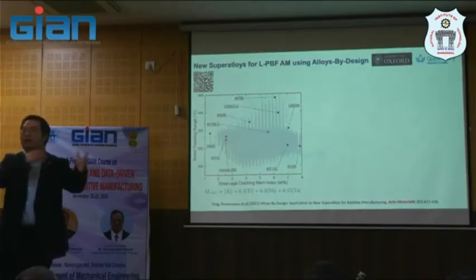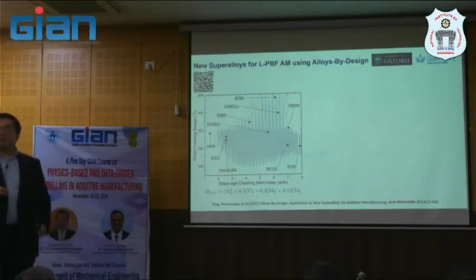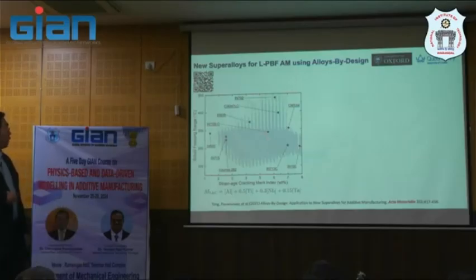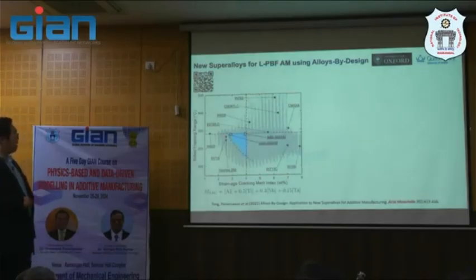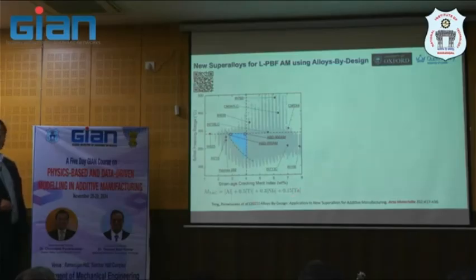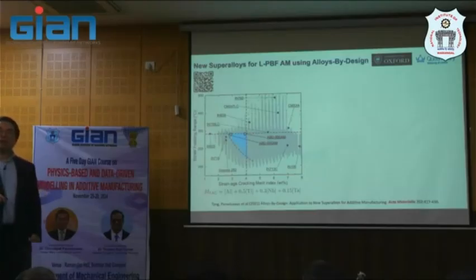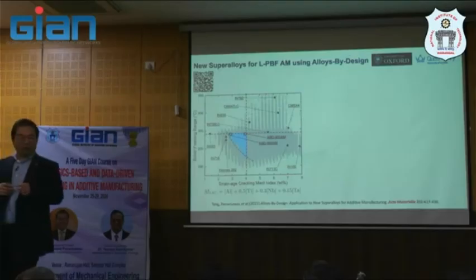We screen, rank, and do a lot of calculation based on the existing nickel-based superalloy database. What we did is use two indices here. I think I repeat it again. One is the strain-age cracking Merit index. Again, this is linked to the gamma prime fraction, but we add niobium and tantalum, which are small fractions, and then we say this is the index. If you vary the content of aluminum by 0.01 weight percent, you will get a combination of the material. Let's say this one varies 0.01, and then another one 0.01, or keep it constant and vary 0.01.